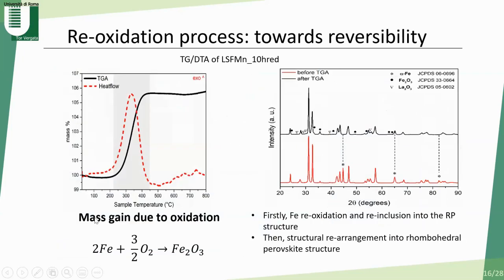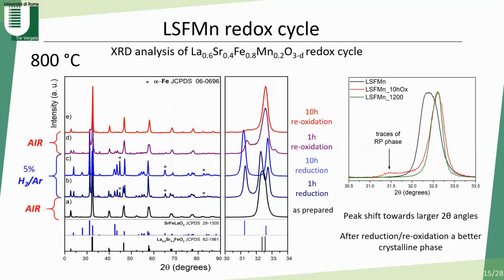Then we investigate the reoxidation, again with the TG, and we can see that between before and after the reoxidation, a mass gain is really observed, and from the XRD pattern we see that iron goes back into the structure, because here we have before and after the TG measurement, with the reinclusion into the Ruddlesden-Popper structure, because in this case the reoxidation is still not complete. Here we have the full redox cycles.